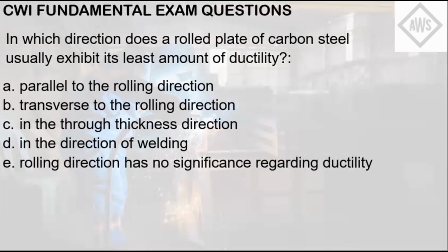This occurs in the through thickness, or the z-axis of the plate, meaning the thickness of the plate. The alignment of grains and inclusions such as sulfides and silicates make it susceptible to lamellar tear. Lamellar tear occurs normally at this through thickness of the plate due to high localized stress, because it is the area of the plate which exhibits the lowest amount of ductility, making it susceptible to that high localized stress, which in this instance is the lamellar tear. So the answer here is letter C.